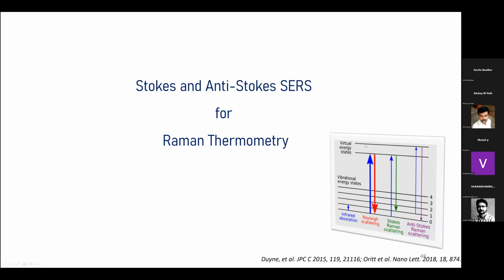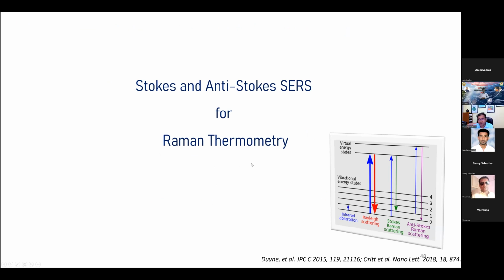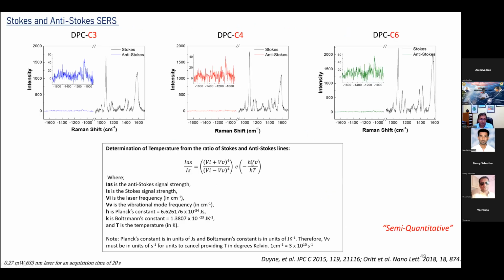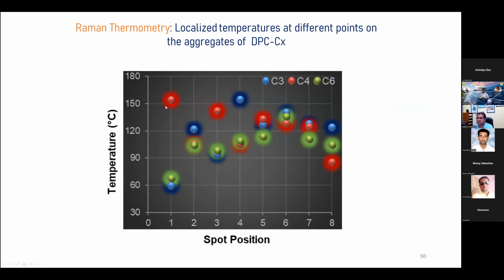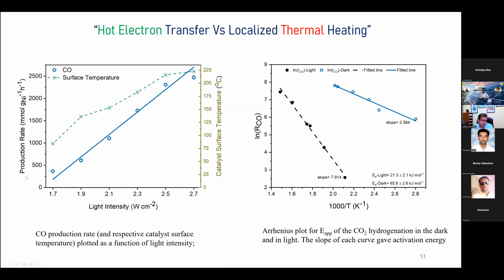Still, we carried out other experiments like phosphor thermometry to measure the surface temperature, and we observed the temperature can go only up to 150 degrees. This is another way of measuring surface temperature, and it again indicates that it has to be hot electron mediated. We also carried out an experiment where we exposed the sample to more and more photons, more and more light intensity, since ideally that should generate more and more hot electrons.